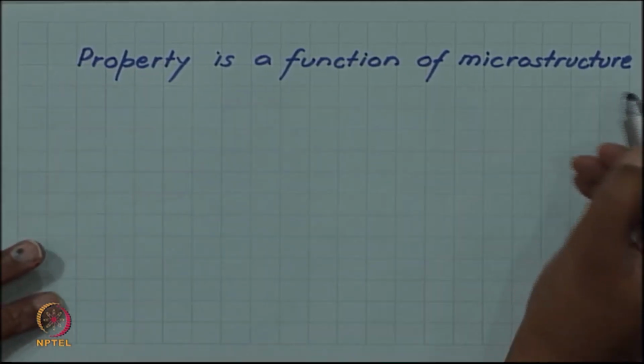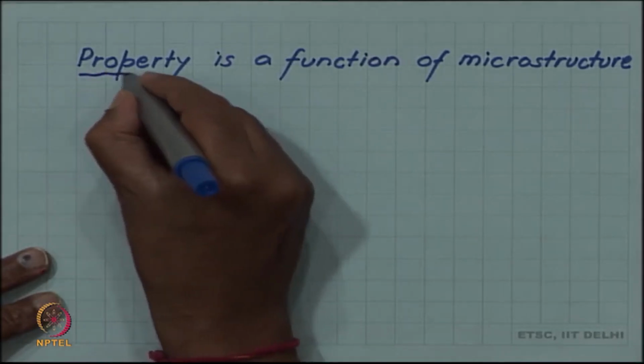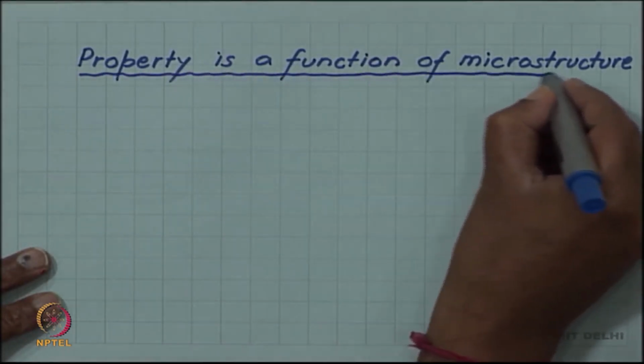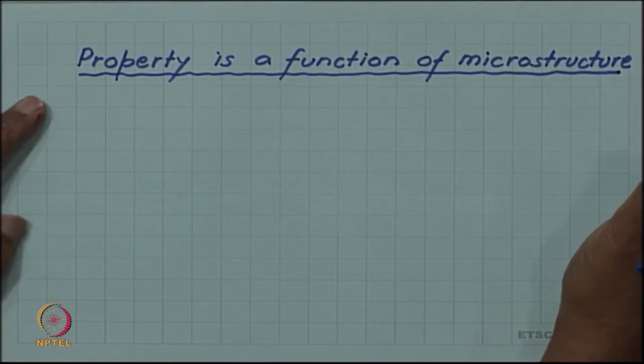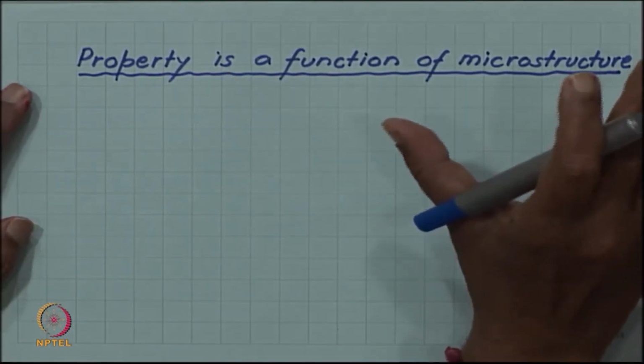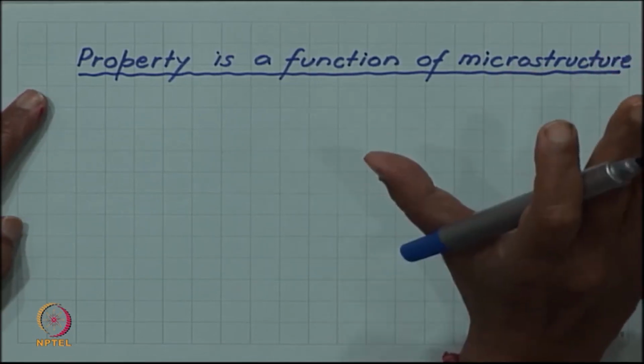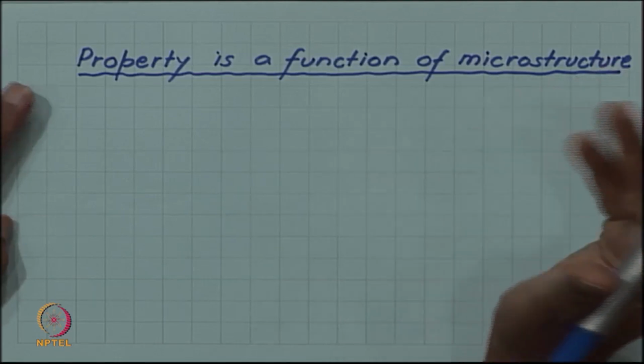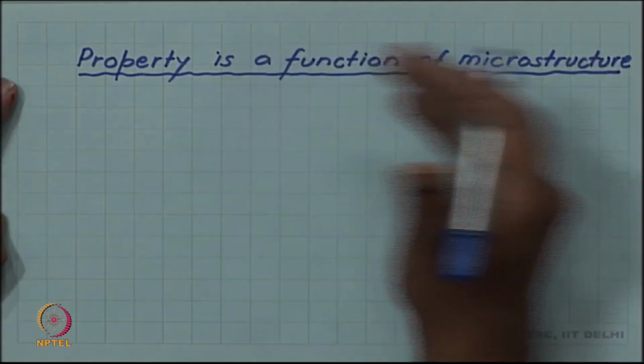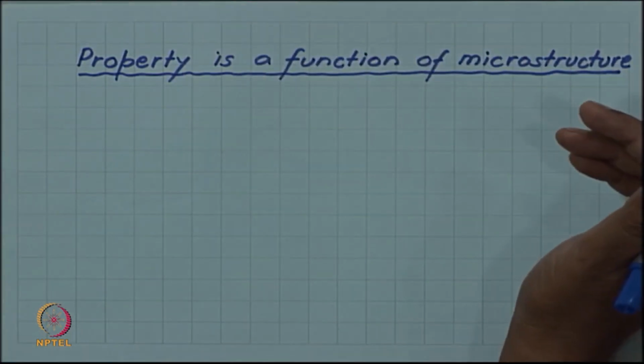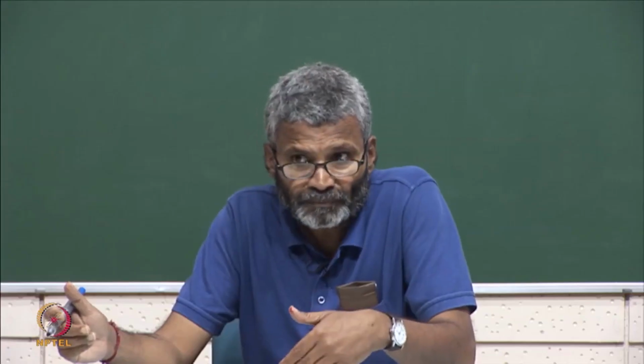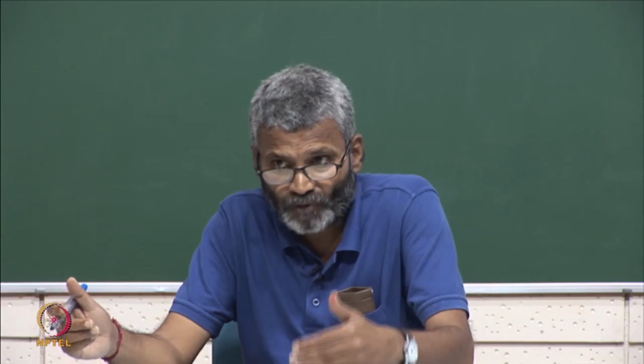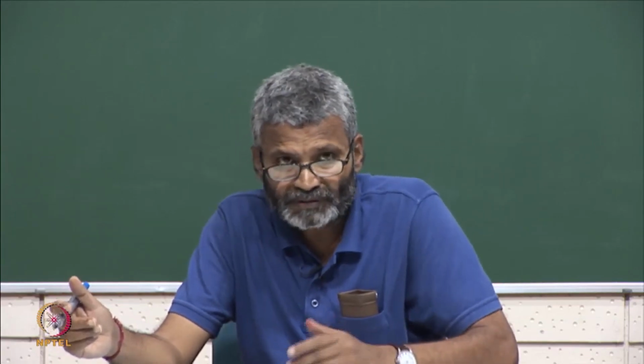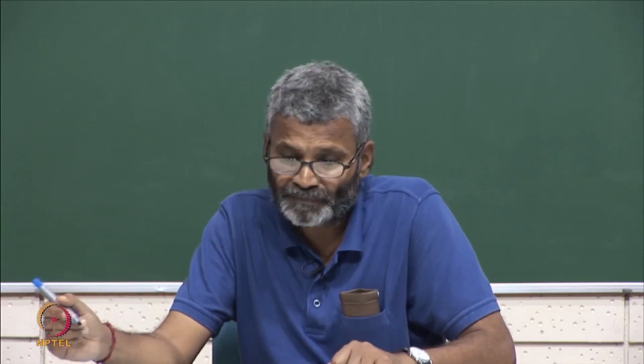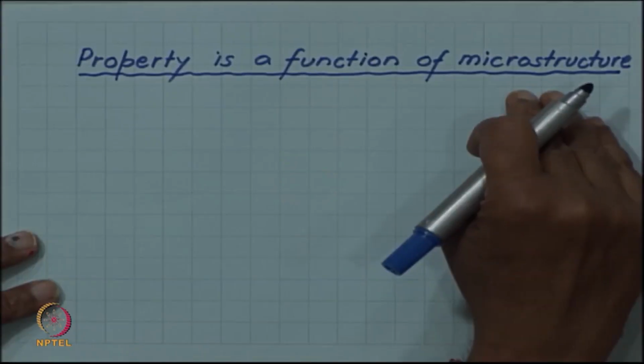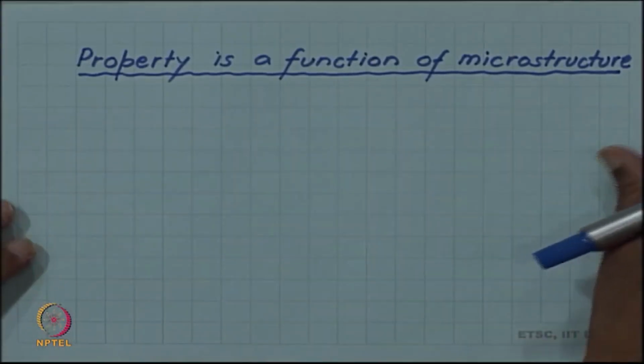So, first of all, property is a function of microstructure. This is our main theme in the material science course, and we have seen this very nicely in particularly in the microstructure and property of steels. We saw that in the same steel of 0.8% carbon, for example, we can get hardness values in the range of a factor of 4. We can get a hardness of 15 Rockwell or a hardness of 65 Rockwell simply by controlling the microstructure. So, microstructure is an important determinant of the property in the steel of same composition.